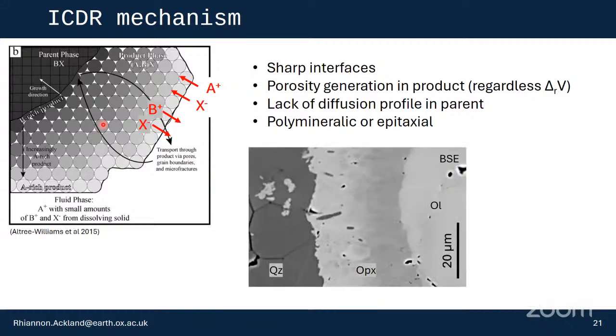So many of the features of the ICDR mechanism we see in my experiments. As I mentioned, the olivine-OPX interfaces are always sharp, and often sharp at the quartz interface too. I do see the porosity generation within my rims; you can see here some examples of this. There's a lack of diffusion profile in the olivine. There's no diffusion profile in magnesium and iron towards the OPX interface. And we don't really expect any diffusion profiles in the quartz. Due to the high degree of mismatch between the OPX crystal structure and olivine and quartz, I see this fine-grained polymineralic growth of orthopyroxene, as is picked out by the iron zoning.